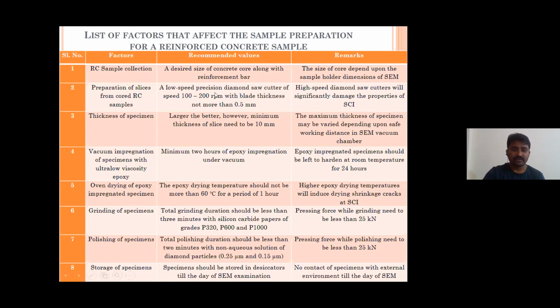Okay. So the speed of the low speed diamond saw cutter can be varied from 100 to 200. If you increase more than 200 revolutions per minute, then there will be some damage induced. So if you want perfectly measured porous zone thickness, then you have to use 100 to 150 RPM. Our low speed diamond saw cutter was in the range of 140 to 150 revolutions per minute, and the thickness of the blade, in our case, was 0.4 mm. You can go even to 0.5 mm at maximum. If you use high speed diamond saw cutters, it will significantly damage the properties of the steel concrete interface. Thickness, vacuum impregnation, as we have discussed, is just summarized here.